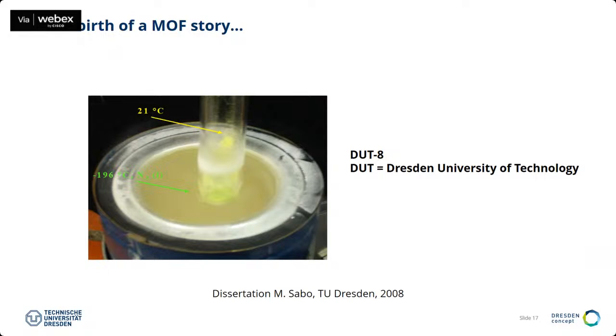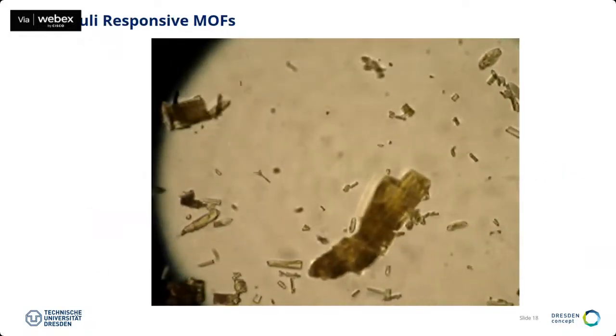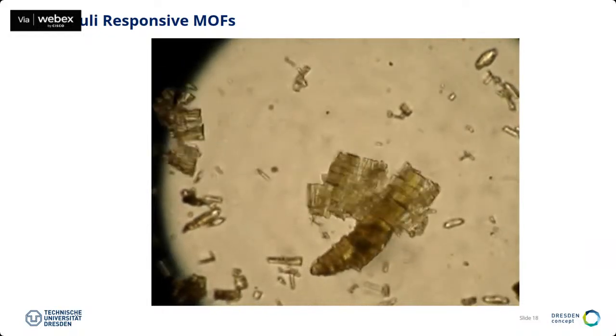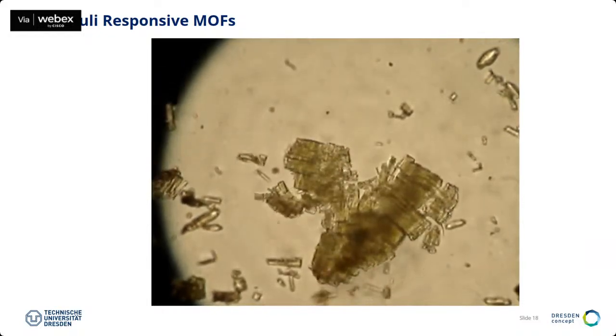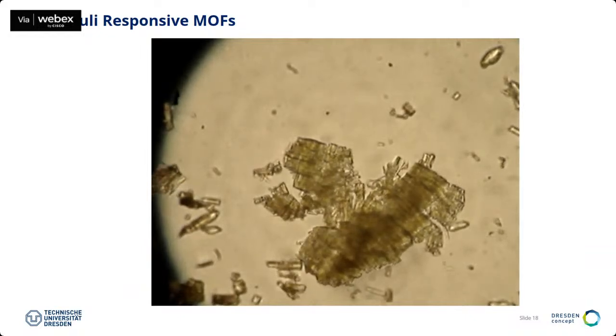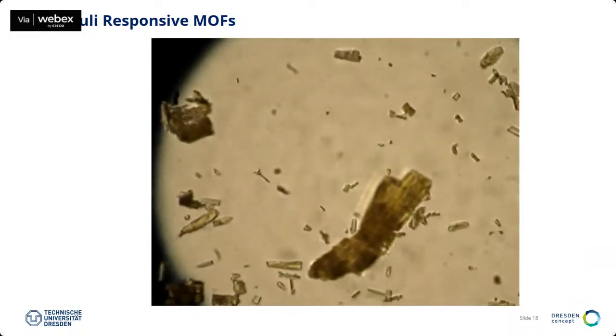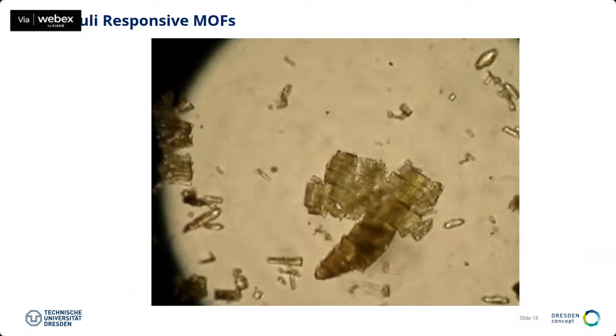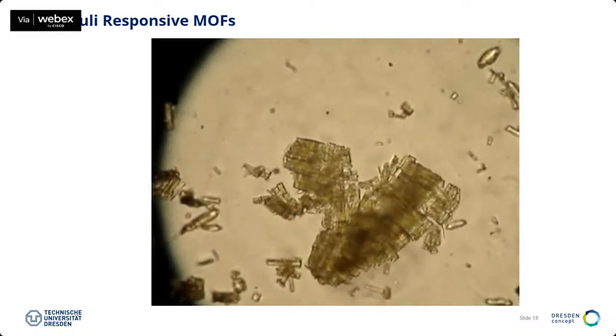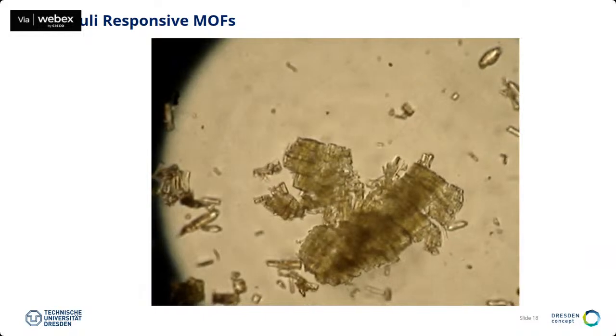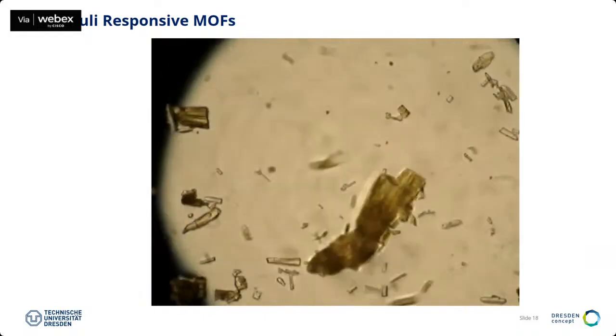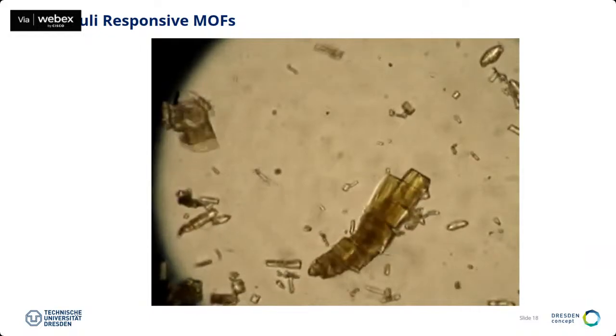And only later, when we started the first experiments where we put these crystals in a microscope and then exposed them to a solvent, we realized what these structures and materials are doing. So here you see the same MOF, we call it DUT-8. And after the evacuation, it forms a closed crystal. This is the closed crystal. And then when the solvent is coming, it shows a huge expansion. So these materials are dynamic materials. They change their structure depending on what's inside.